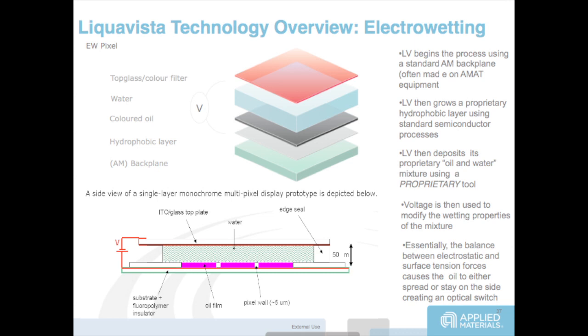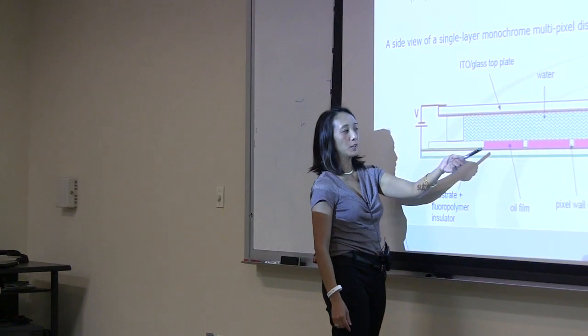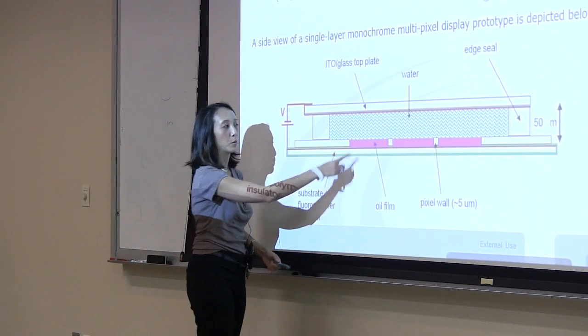Then you deposit an oil and water mixture. With about a million dollars, a material scientist could probably come up with a material that works on a hydrophobic layer — it's not a lot of capital equipment. Then you drive voltage to move this mixture. What you've just done is eliminate the liquid crystal — the oil and water itself becomes the thing that causes the color. This is both a shutter and a color element, because if you make it RGB and it shifts on and off, that's your color.